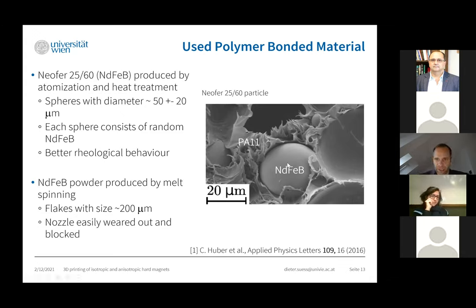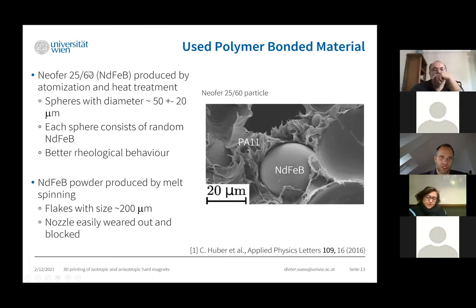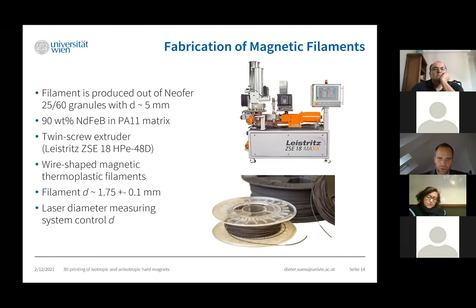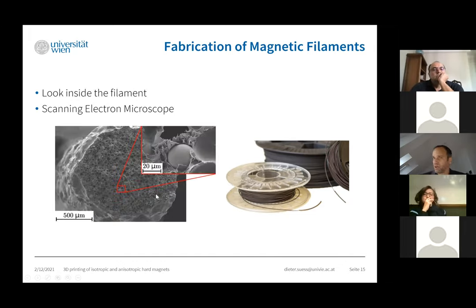And these materials, like neodymium iron boron with PA11, exactly these Neofer 25/60 granules, are usually used for injection molded magnets. We used exactly the same material just to produce magnetic filaments using a screw extruder, and one ends up with this filament with a diameter of about 1.7 millimeter. And of course the diameter is very important. You only can allow for about 0.1 millimeter in variation, otherwise you can't print it any longer.